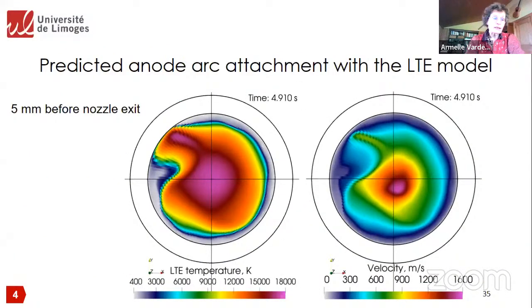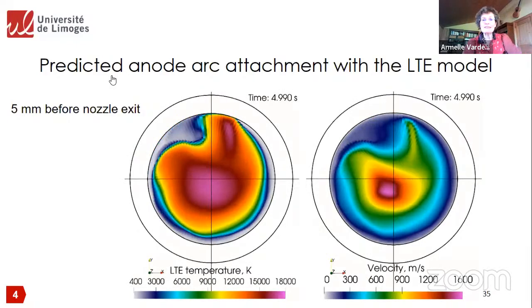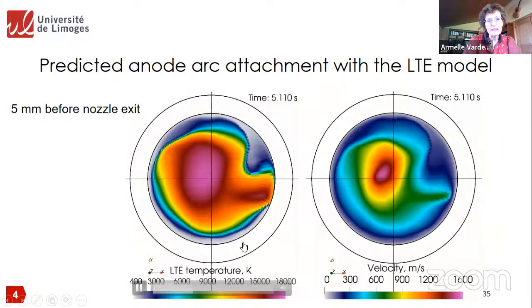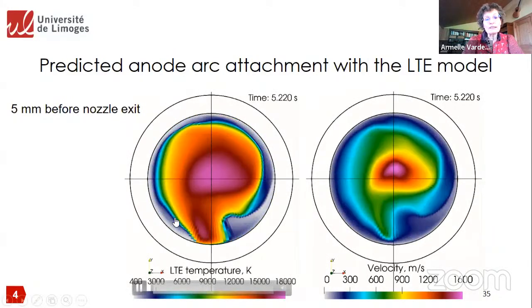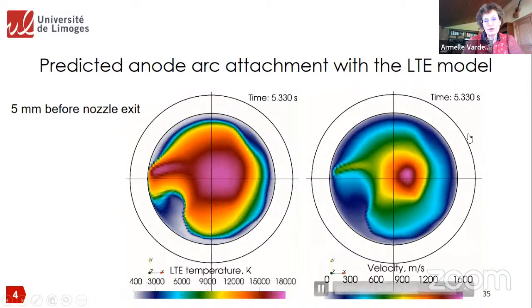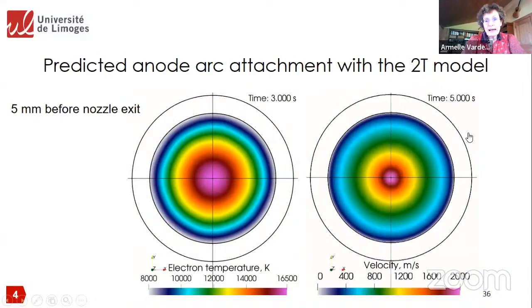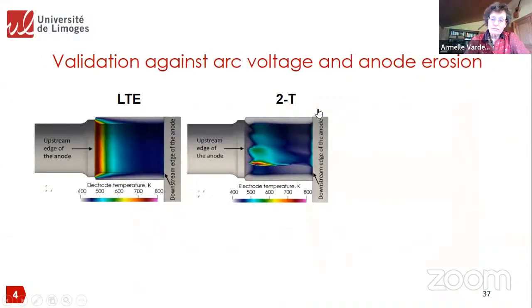If we look now at the velocity and temperature profiles we get at the nozzle exit, this is a cross-section of the nozzle, and you can see here that with the LTE model, we have some rotation of the arc, and this rotation is induced by the swirling injection of the gas. Now, if I look at the nozzle exit with the two-temperature model, you can barely see any movement of the arc. You just have to see that here. The arc hardly moves. But which model is correct?